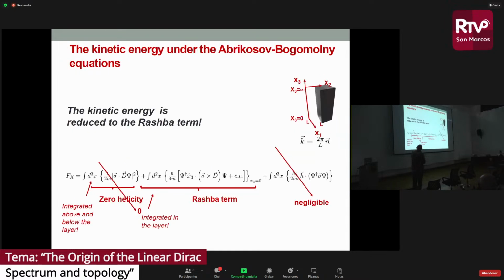So there it is. It vanishes. Then I have a quartic order term here, because H local field is proportional to psi conjugate psi, so this is a fourth order term. I cannot show you here because of lack of time, but that's a negligible term. And what I am left with is essentially the Rashba term. Notice that it's a three-dimensional identity there, but I can take the surface, because I had a divergence, and this becomes a surface term, which is integrated on the surface of the layer, above and below. So that's all that is left.